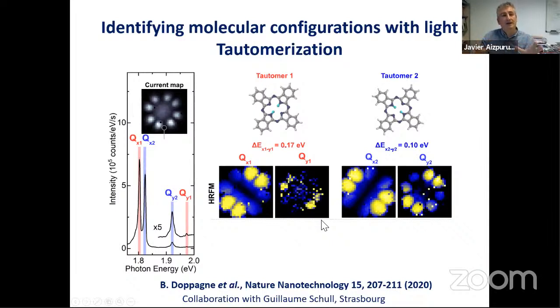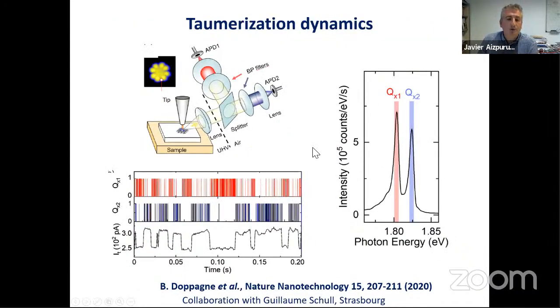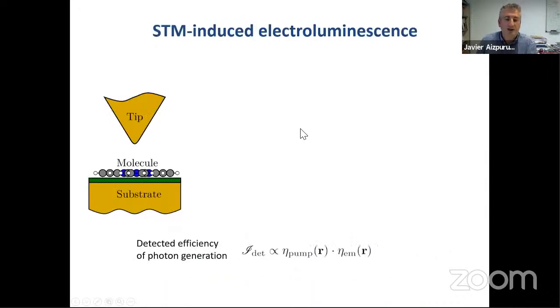And now we have to apply, in this last couple of minutes, all I have told you about the pico cavities, the coupling strength, and the molecule extension to interpret this result. Again, this experimental image of the emission is quite complex. You see here that it's orthogonal, but you see here two yellow maxima, blue cut here in the middle. It's quite complex, right? So now this is what we need to describe. Again, these two emissions of the tautomers. And what we do is, as I said, apply what I just described in the whole seminar.